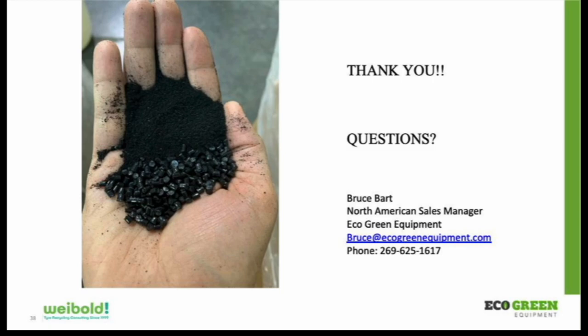So if you were using say a 50% regrind of this material and you already have 50% rubber in it, and then you put our same 50/50 in as the virgin material, then technically your recycled content is more than 50%. So you may have some adjustments to make. The more of this recycled material you put in, if you're using the same material on the infeed in pellet form, then your percentages of recycled material content, or rubber I should say, are going to go up.